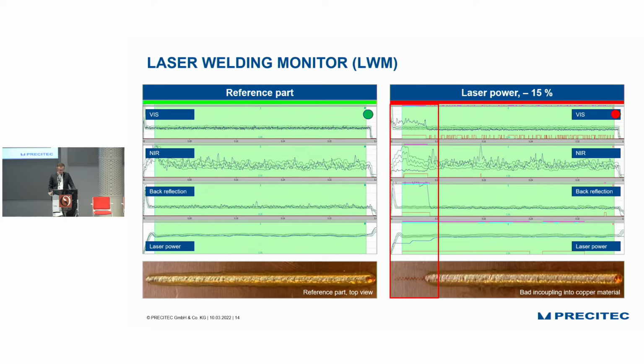Now we intentionally apply defects such as a decrease of laser power. So here we have an intentional decrease of laser power. This means infrared is not coupling into copper. It is severely back reflected. And here we get high signals on our photodiode, which is sensitive to the wavelength of your laser source, as can be seen here. And the moment the incoupling takes place, the back reflecting signal goes back to normal, in between the references. So we can see the incoupling event of infrared in copper, which might be of interest in the field of hairpin welding.